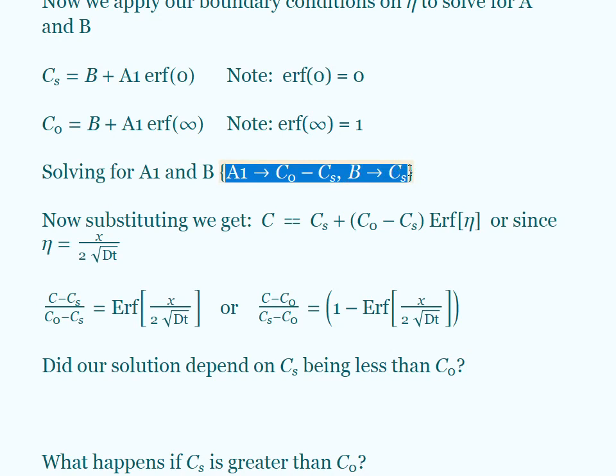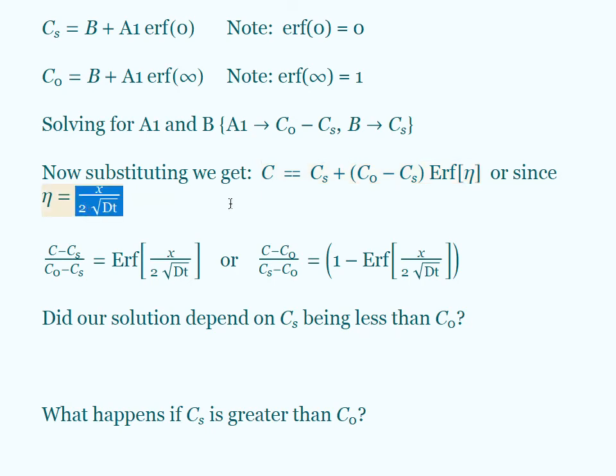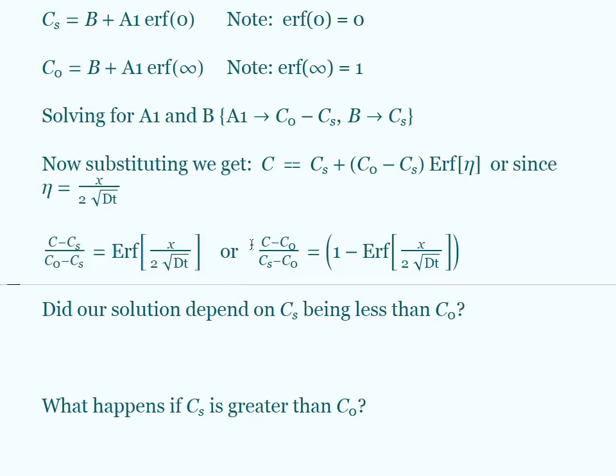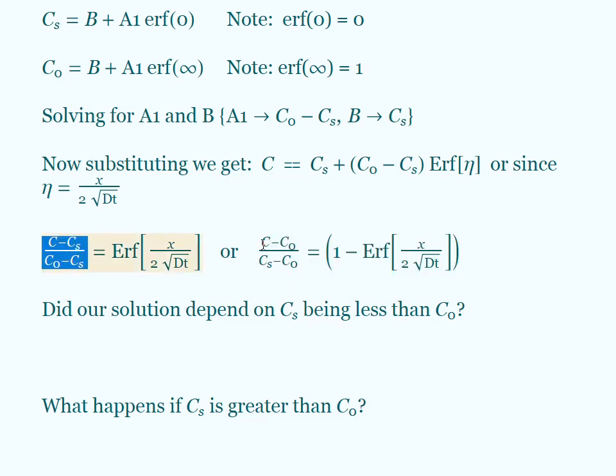We substitute those in. So there's our solution then in terms of C. Remember, this eta is equal to x over 2 times the square root of Dt. So we can substitute that in now as well. And the standard form for this equation, these terms are generally moved over to the left side, so it might look something like this. Or an even better form that we used in 2044 is this one. So I just did some rearranging here with the Cs and C₀s to give us this form here. And that brought this 1 in here. This is a nice form because it gives the concentration, this is what we're solving for, relative to the initial value of concentration. And then it divides by the surface, again relative to the initial.